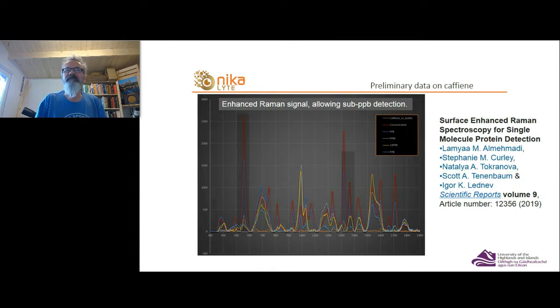spectrum. So this spectrum is looking at just a simple caffeine molecule, because we just wanted to exhibit the sensitivity of our technique. Essentially, without going into too much detail, the orange spectrum at the bottom is standard Raman on a concentrated amount of caffeine in liquid. But if you then go up to some of the spectra with the higher peaks, those are using our substrate, but we're dramatically reducing the caffeine concentration. And we're at the point now where we can measure between parts per billion and parts per trillion of caffeine in liquid, which is quite a stunning measurement to make.